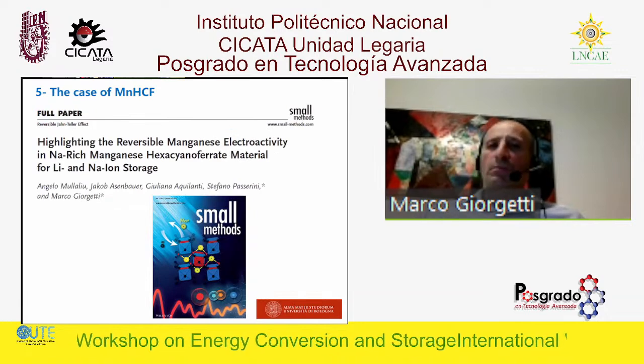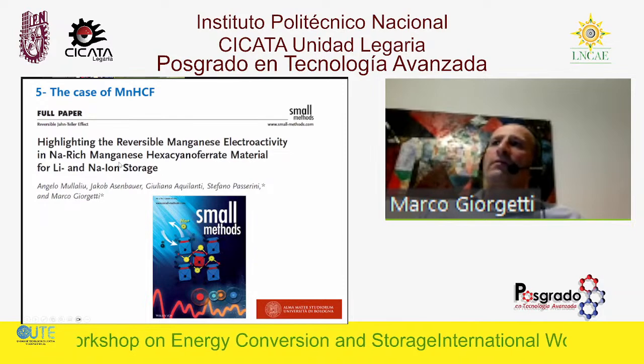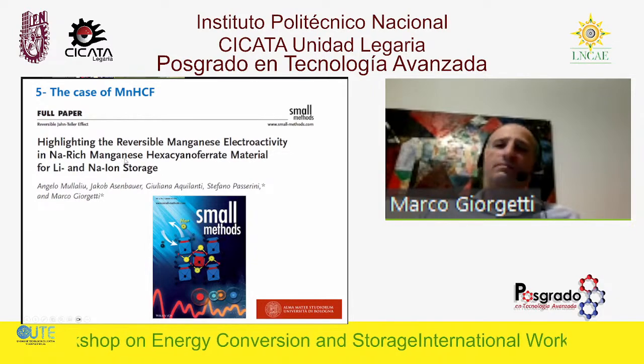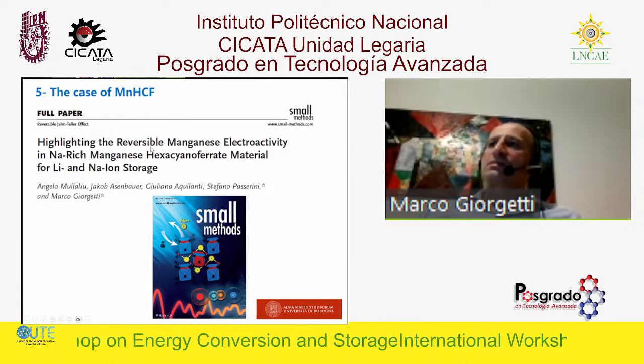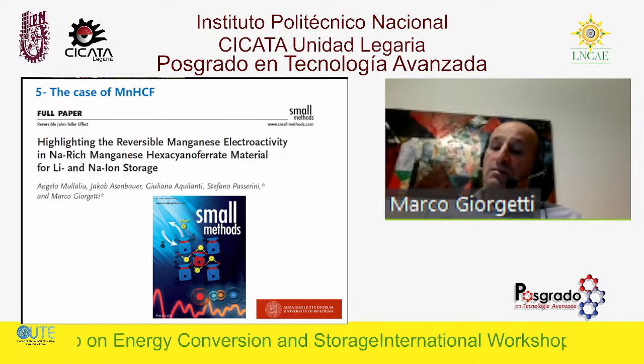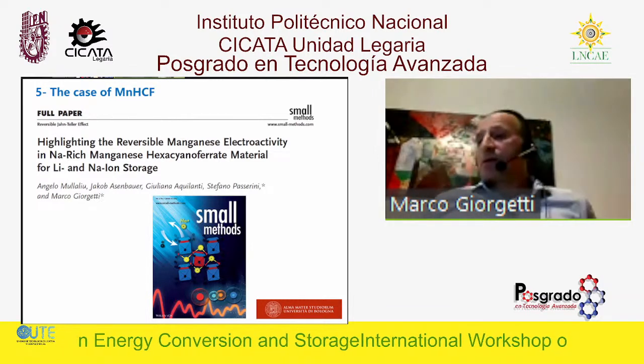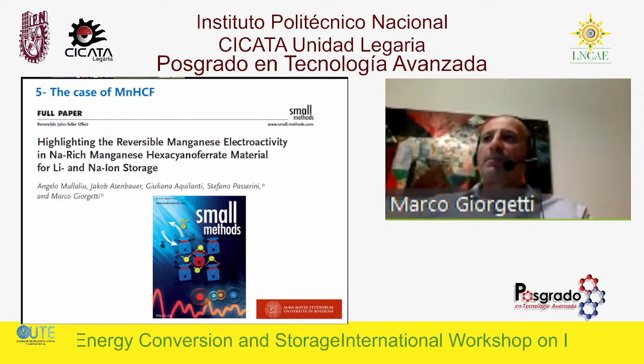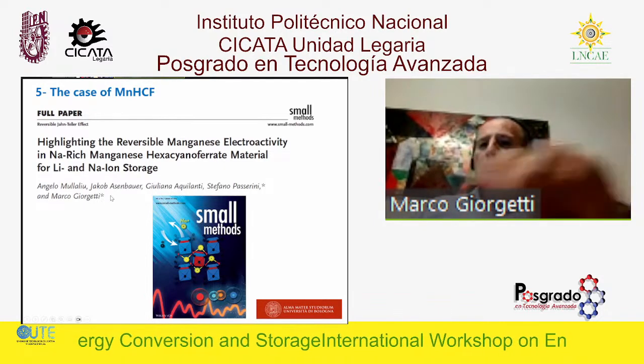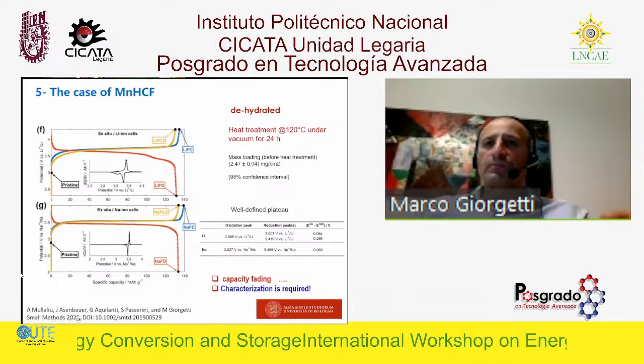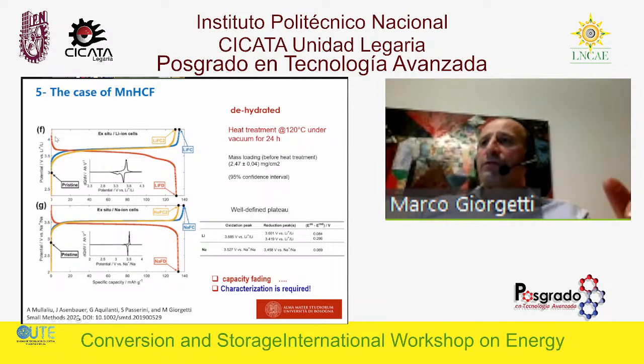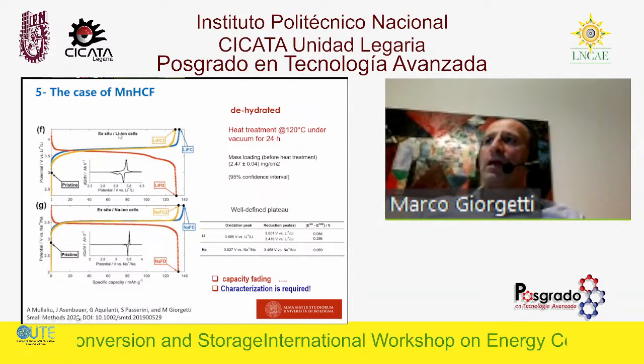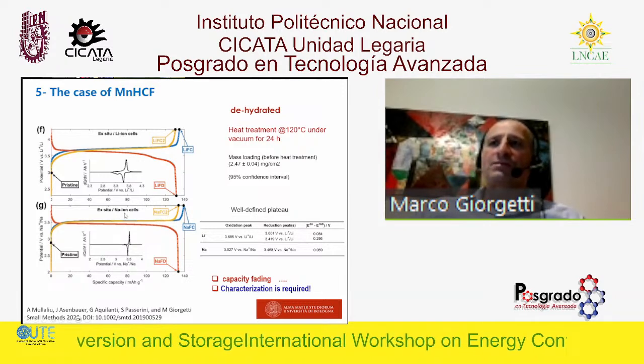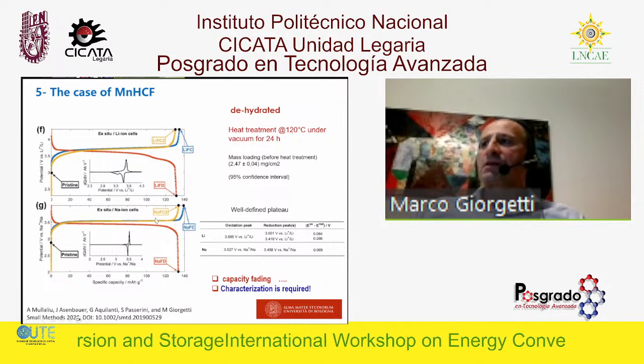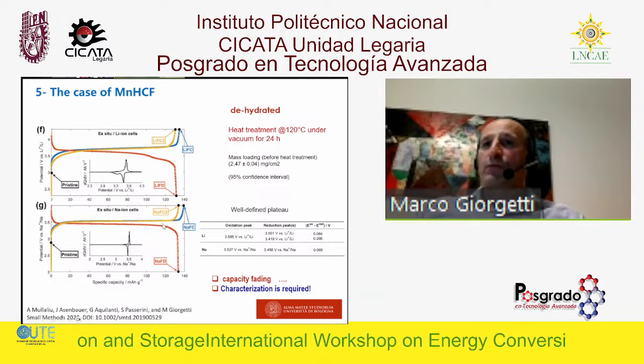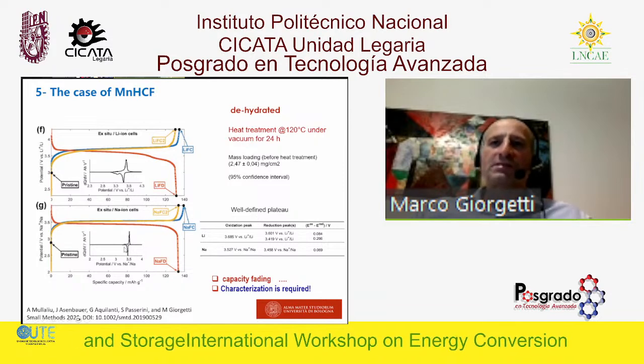Probably today, one of the most interesting aspects that we have on the metal cyanoferrates is due to the manganese. The manganese cyanoferrate is very interesting because you're going to see that the specific capacity, the reversible capacity, is very high, as indicated here. So this is the electrochemical behavior on the lithium-ion half cell and on the sodium-ion half cell. First of all, it's a very interesting plateau. The plateau is very straightforward, such as in the case of lithium iron phosphate, for instance.